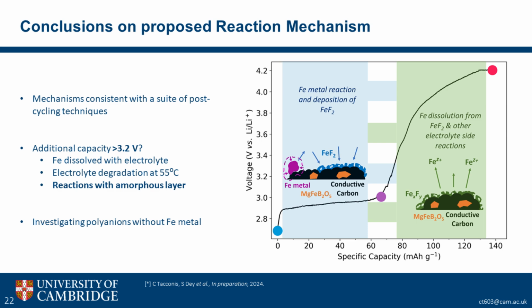And this is something that I've been investigating in my current projects, is that we think there's an amorphous borate coating on our materials, and that this could be undergoing further reactions, which just go away at the end of the first charge, and they're not reproducible. And so we are investigating this mechanism in polyanions without iron metal impurity.